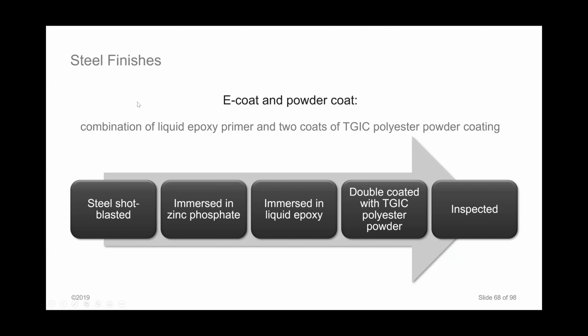The E-coat and powder coat finish is a premier steel coating and is a combination of liquid epoxy primer and 2 coats of TGIC polyester powder coating. The process has 5 steps. First, the steel is shot blasted to the specification of SSPC SP10, shot blasted to near white condition, removing all oil residue, mill scale, weld spatter, and slag. The steel is then immersed in zinc phosphate in an 8-stage pretreatment process. Then it is immersed in an electrostatically applied liquid epoxy and coated to a uniform 0.7 to 0.9 mils. This E-coat totally encapsulates the part, preventing rust.